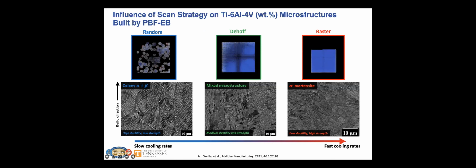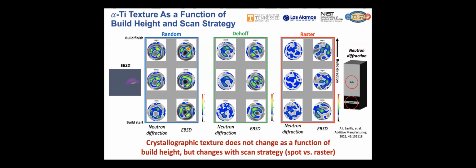So down below, we have as-built microstructures. And we can see that for random, we tend to form more colony alpha plus beta microstructures. And at faster cooling rates, we tend to form more alpha prime martensite types of microstructures in the as-built condition. So one thing that we did is we started looking at the as-built texture as a function of build height and scan strategy. So this was done with neutron diffraction at Los Alamos National Laboratory.